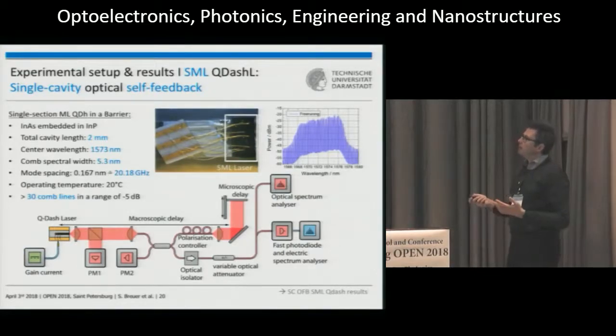And in this case, we do exactly the experiment. We use a laser, we delay the optical light, it's fiber-based, into the laser, and we do exactly this optical feedback experiment as discussed before. The laser is emitting at 1573 nanometers.